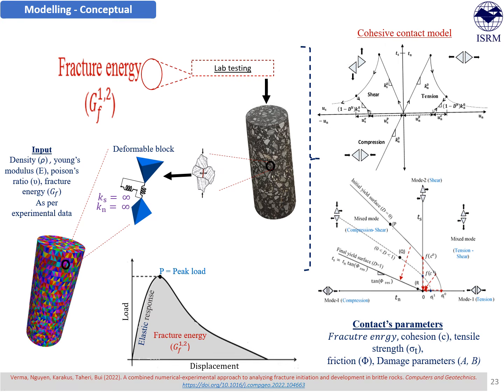Now to mimic that fracture process numerically, in 3DEC we use 3D tetrahedral blocks. These 3D tetrahedral blocks were made deformable via zones, and they interact with each other via a contact model. Now this contact model plays an important role in capturing the intergranular cementitious forces. Now to capture that